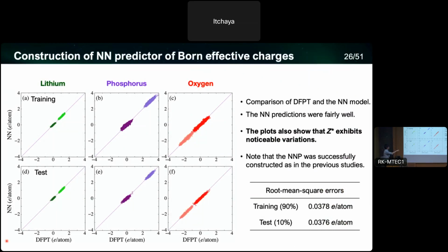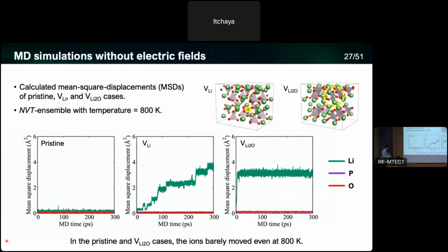And as I mentioned, the formal charge is not always the case. So depending on the atomic environment, the oxygen charge changes from almost -3 to around -1. So considering the local environment may be important. So this is the error of our model, which is not very small, but this is an acceptable size of error. So we proceed to the molecular dynamics simulations.